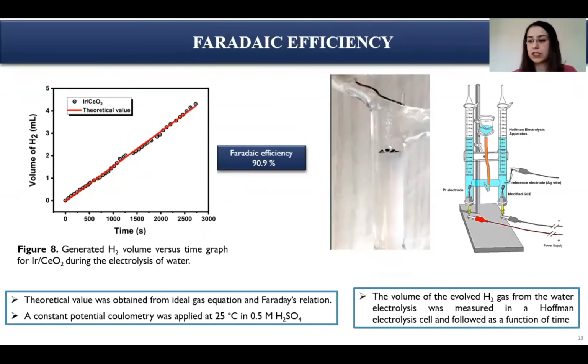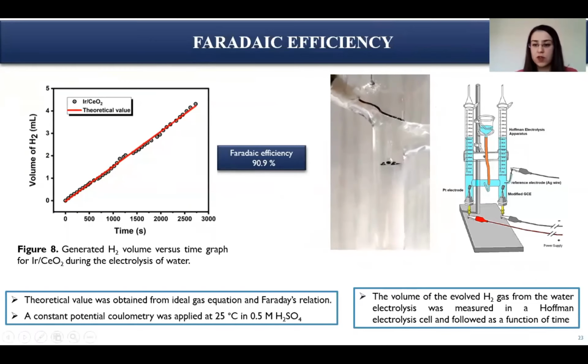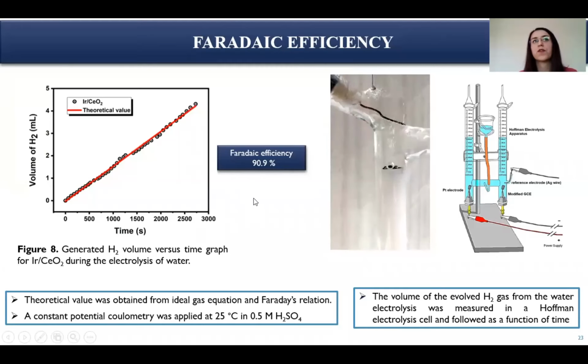The Faraday efficiency during the hydrogen production was also determined using an iridium ceria modified glassy carbon electrode. It was calculated using the water displacement method via a Hofmann apparatus. The volume of the evolved hydrogen gas from the water electrolysis was measured in a Hofmann electrolysis cell and followed as a function of time. The Faraday efficiency was calculated as 90.9%, which is well consistent with the other catalysts reported in the literature.